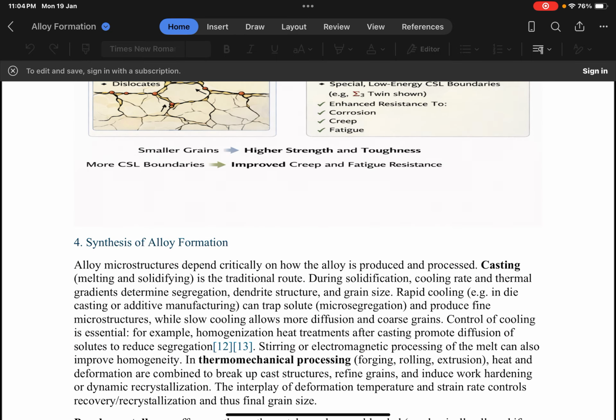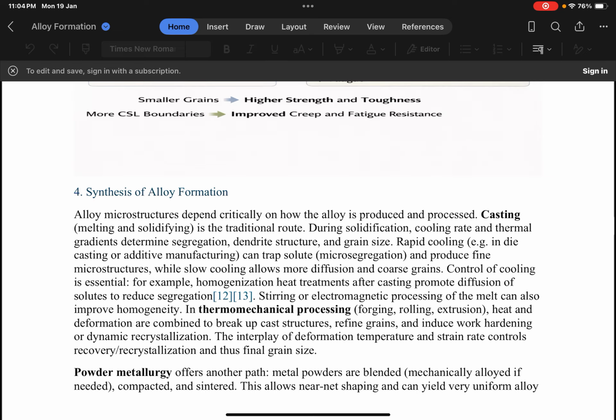Alloy properties depend strongly on processing method. Now I will talk about the synthesis of alloy formation. Alloy microstructures depend critically on how the alloy is produced and processed. First method is casting. Casting, meaning first melting and then solidifying, is the traditional method. During solidification, cooling rate and thermal gradients determine segregation, dendritic structure and grain size.